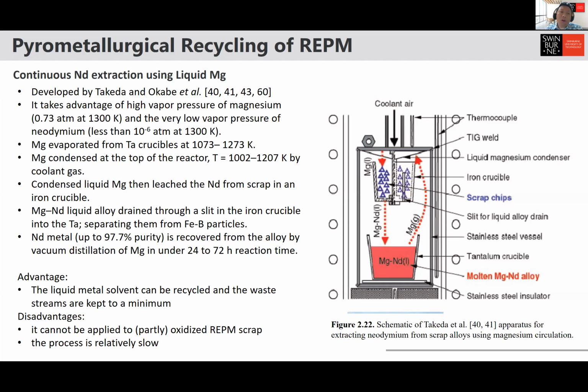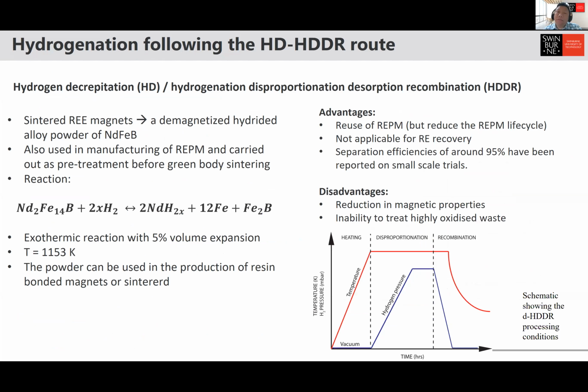Right, there's also a process called hydrogenation. In essence, hydrogenation is where you try to react hydrogen with the NdFeB, with the magnet, right? This is sort of in line with what is called the HDDR route. I didn't put it in here. When you manufacture the magnet in the first place, there's a process called HDDR. It's called hydrogen decrepitation, hydrogenation, disproportionation, desorption, recombination, right? So in the original process when you manufacture a magnet, you can actually melt NdFeB, right? You have a particular composition of NdFeB and then you melt it and cast it.